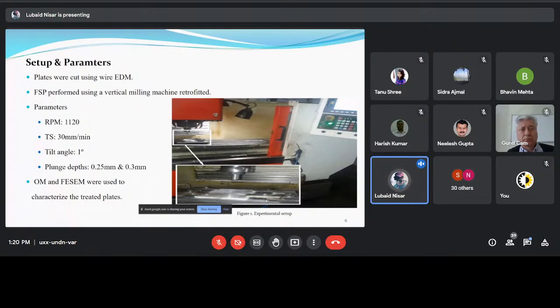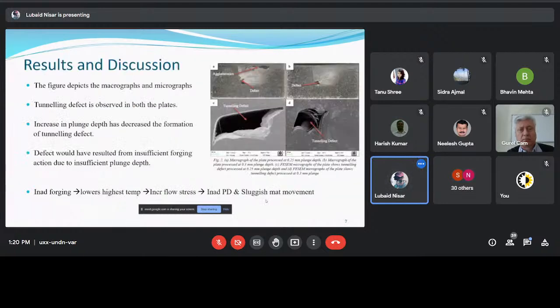The plunge depth was varied. We actually used two plunge depths, which are 0.25 millimeter and 0.3 millimeter. Then optical microscopy and field emission scanning electron microscopy were used to study the particle distribution and microstructure of the processed plates.